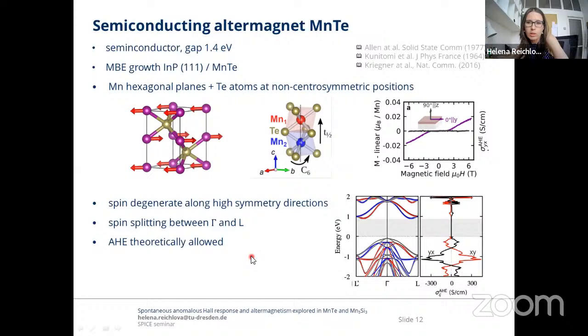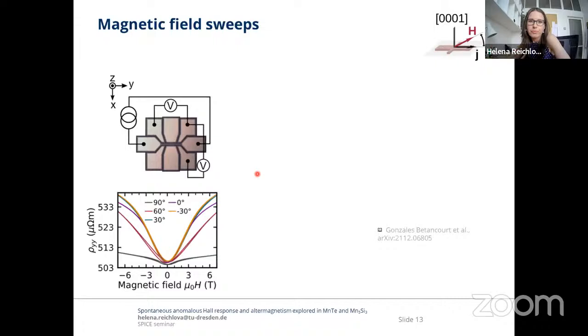And this brings me to the measurement itself. So what we did, we prepared Hall bars of manganese telluride. The current is applied in the channel of the Hall bar, and longitudinal and transversal voltage is measured. The longitudinal measurement shown here exhibits AMR, anisotropic magnetoresistance, a well-known effect, nothing surprising.